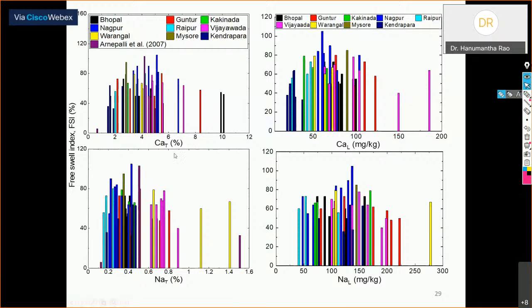Here T designates the total calcium present in that soil, and L designates leaching of this calcium from the total calcium. That's why the Ca total is expressed in the form of a percentage, while leaching is expressed in milligram per kg. This leaching may be 100% or maybe 10% or in between any range. We do not know, and I also do not have any idea how to confirm how much percentage of this leaching is from the total.